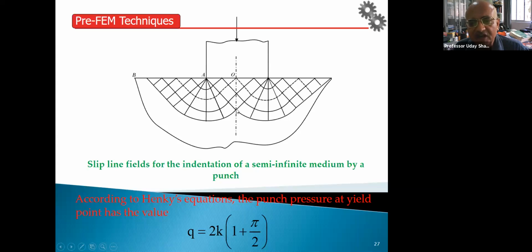Now the slip lines can be constructed in a heuristic way, or they can be constructed in an analytical way. Say for example, we can say that in this plane there is no vertical stress, so therefore this must be one principal plane, and therefore the shear stress should be at 45 degrees. Like these type of logics you can put, and you can construct the slip line field for the indentation of, suppose, a semi-infinite medium by a punch, and then you do the analysis and you can get that punch load will be 2K (1 plus pi by 2).